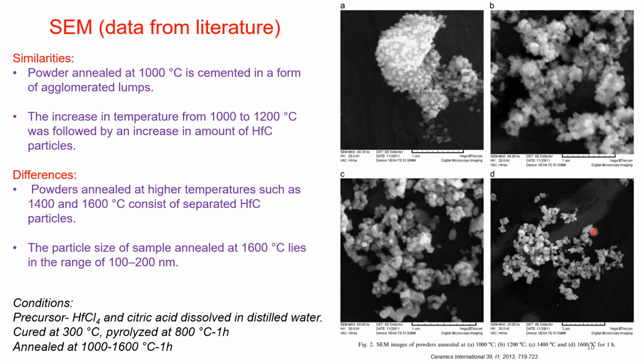Now, the precursor that was used in this study was hafnium chloride and citric acid dissolved in distilled water. And the samples were initially pyrolyzed at 800 degrees C, which were then further annealed for 1 hour at higher temperatures, which suggests that any additional annealing may produce separated or equidistant particles in our samples as well.